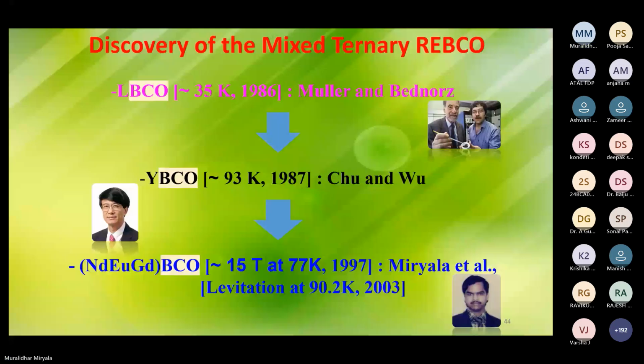However, this YBCO, when you apply a magnetic field of around 3 to 4 Tesla, goes to zero, so we cannot use it for high field applications. Then what I did: yttrium was replaced by several rare earth materials, more than hundreds of materials being worked on. Then we found one of the materials, neodymium, europium, gadolinium, can trap more than 15 Tesla at 77 Kelvin. This also showed levitation at 90.2 Kelvin. This clearly indicates that one can make very powerful magnets, which can be useful for fusion, transportation, as well as better medical applications.